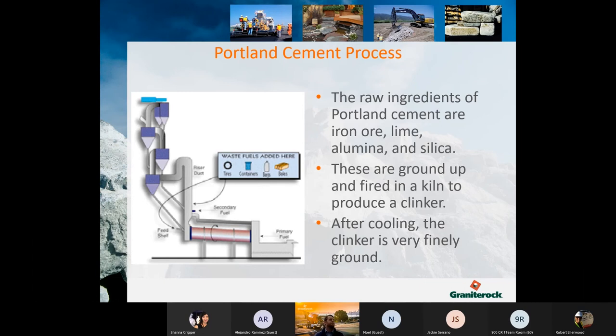On the left, you can see bins. Those are fed into a large rotating kiln, which is heated to about 2,500 degrees Fahrenheit. All the components bind together and cook basically and form a product called clinker. Once that clinker has cooled, it is ground down into the fine powder, which is what we call Portland cement.